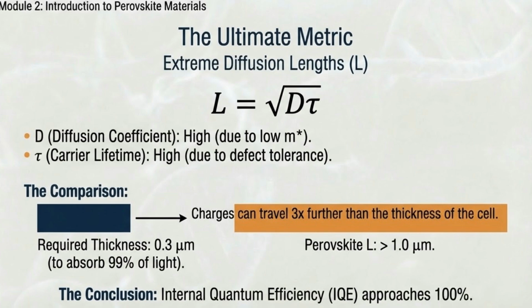Why is this the ultimate triumph for this material? Look at the graphic at the bottom of the slide. Because perovskites are incredibly strong light absorbers, a solar cell only needs to be roughly 0.3 micrometers thick to absorb 99% of the incoming sunlight. If your film is only 0.3 micrometers thick, but your charges are capable of traveling for over 1.0 micrometers, they can travel 3 times further than the actual thickness of the cell. This virtually guarantees that almost every single electron and hole generated by the sun will successfully reach the extracting electrodes. Consequently, the internal quantum efficiency of the device approaches absolute perfection.